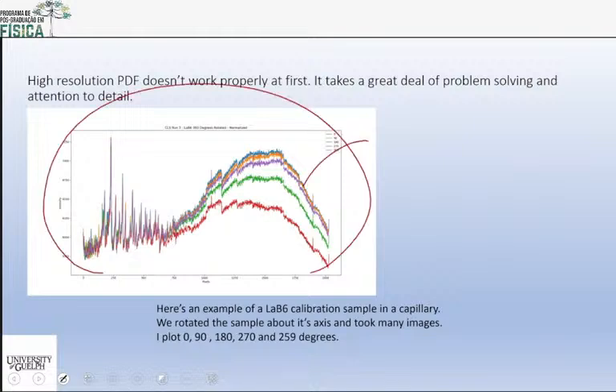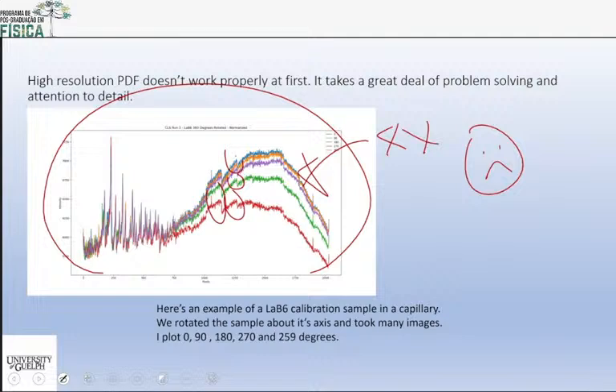This is not good. This is bad, okay? We rotated the sample, it was in a little tube, like a 1 millimeter tube, and it's a standard sample. And as we rotated the sample, we got completely different patterns, and it was terrible. And we also saw these terrible glitches. This is not good. We had to solve a lot of problems.